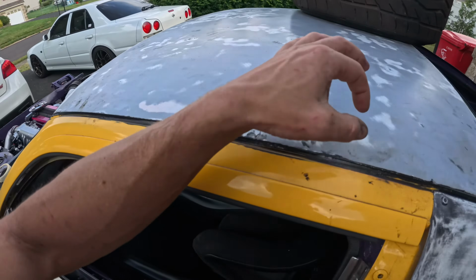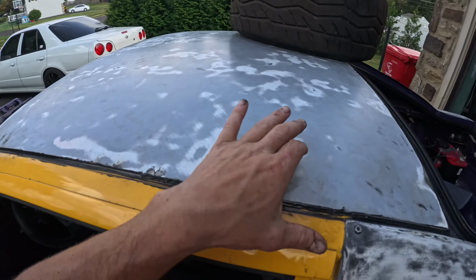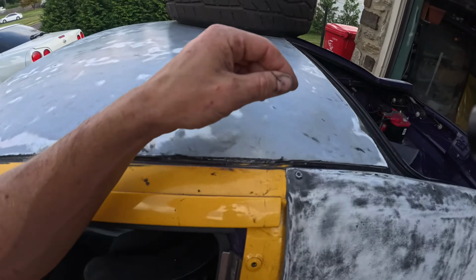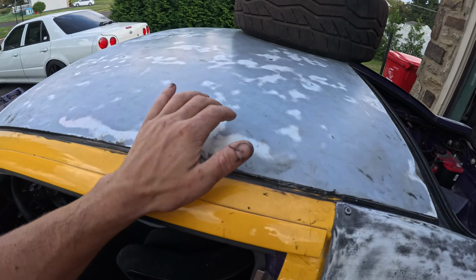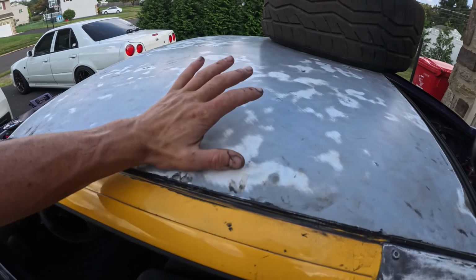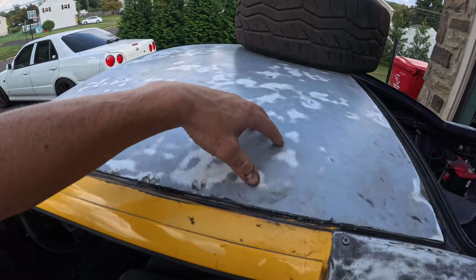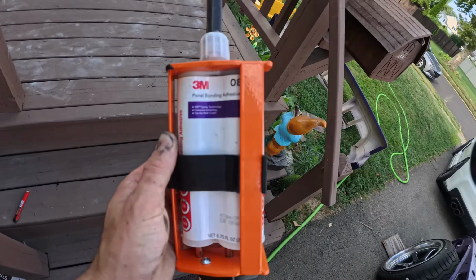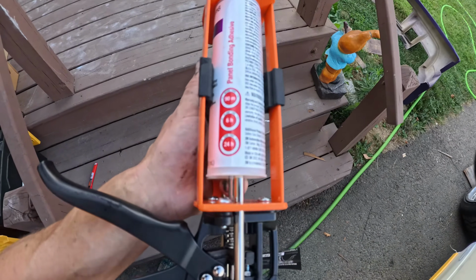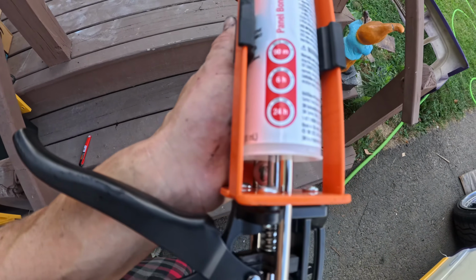After removing the paint from the metal roof using a flap disc, I applied the 3M panel bond around the border and evenly spread it using an etching brush. It is critical that you completely cover any bare metal using the adhesive to avoid any future rust. This particular adhesive has a 90-minute work time, 6-hour clamp time, and 24-hour cure.